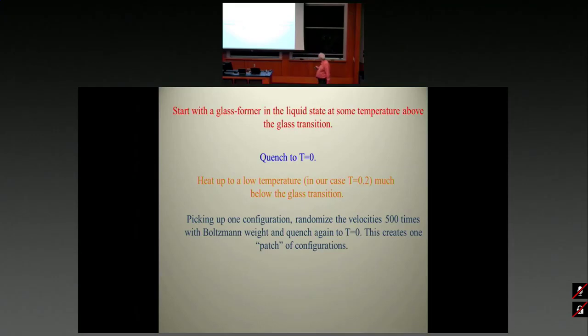Let's say 500 times. Of course, this is arbitrary. It could be 1,000 times or 300 times. And the randomization is done with the Boltzmann weight at this temperature, 0.2. So these are legal configurations at that temperature. We do it up to 50,000 particles. I'll show you also system size dependence in a moment. And now when you have done it, quench again to T equals 0. What this creates is what we call a patch of configurations.